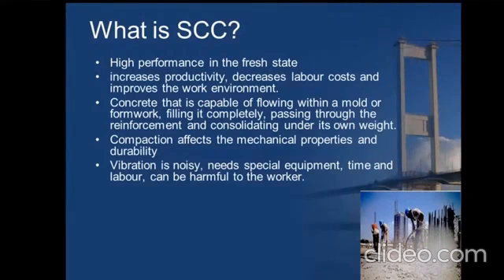And here I would appreciate the use of chemical admixtures, which play a major role. In terms of VMA, viscosity modifying agents, in terms of superplasticizer, and also mineral admixtures like silica fume and fly ash. We call something the paste volume here generally. So paste volume and aggregate volume, these are the two aspects which should be considered while designing self-compacting concrete.